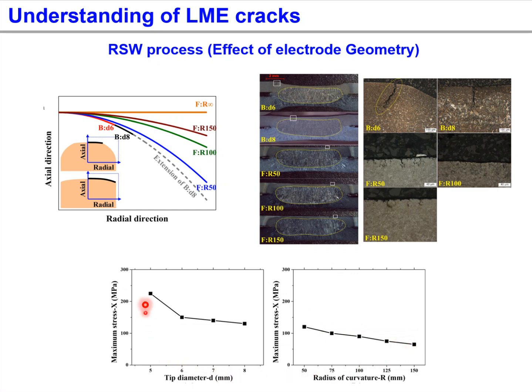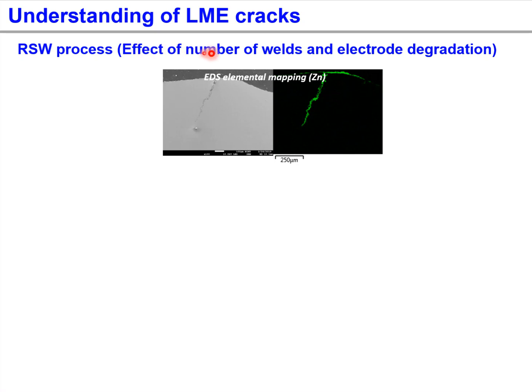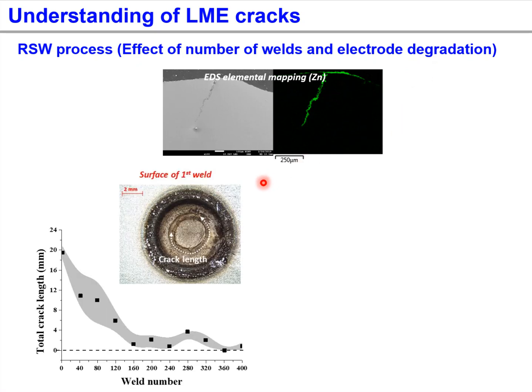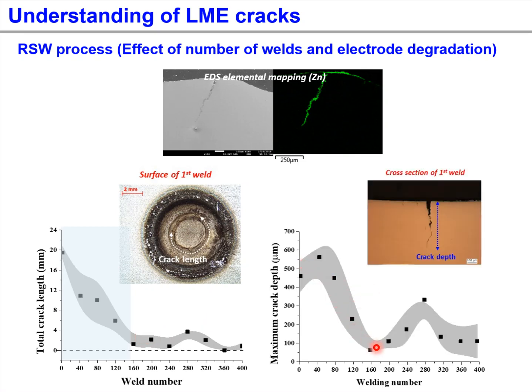This is attributed to the fact that the radius type electrode provides the benefit of an increase in both radius and electrode tip diameter. We also investigated the effect of number of welds and electrode degradation on LME cracking. The first weld was made with a high current level, which resulted in large LME cracking. With an increase in weld number, a dramatic reduction in total crack length and maximum crack length was observed up to around 160 welds, and further welds show relatively low levels of LME cracks.